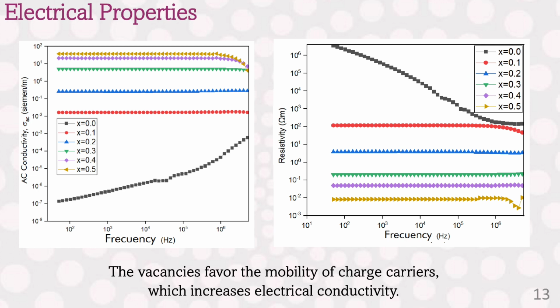Resistivity data were obtained, which indicates by its values that it is a semiconductor-type material. It can be observed that as the concentration of the dopant increases, the resistivity decreases, which is related to the increase of vacancies that favor the mixed conductivity of the material and are associated with the difference in valence that exists between iron and nickel. That said, an increase in conductivity is also observed with some saturation values related to random diffusion of charge carriers.